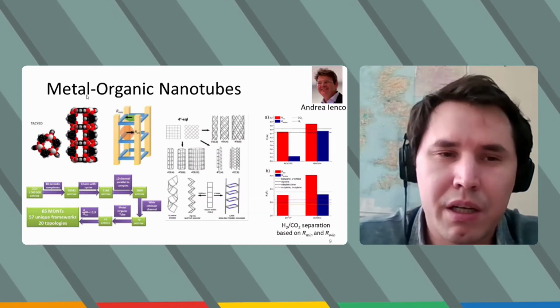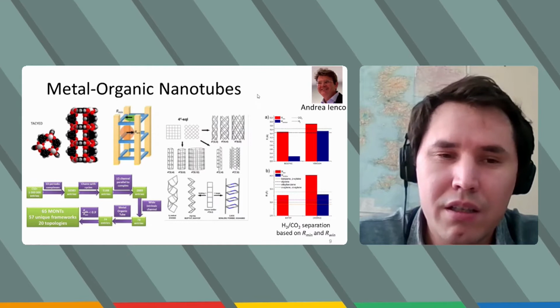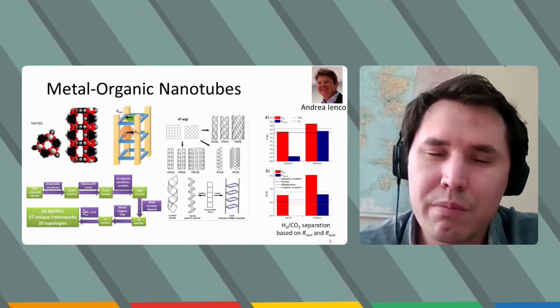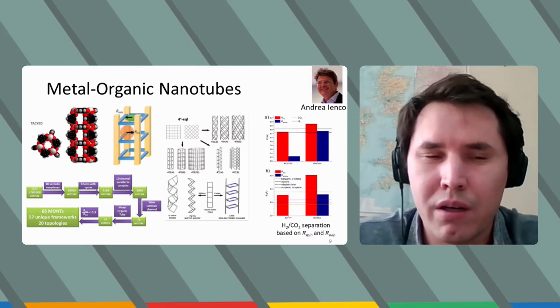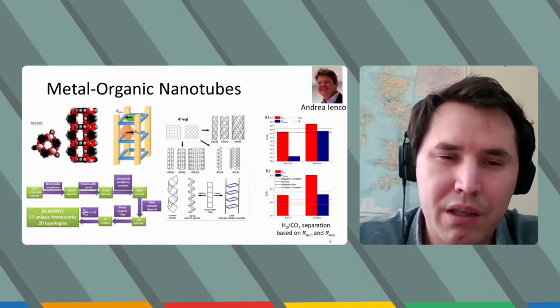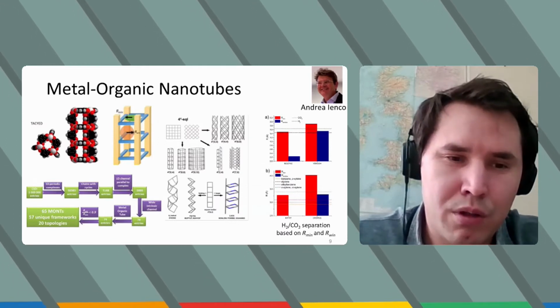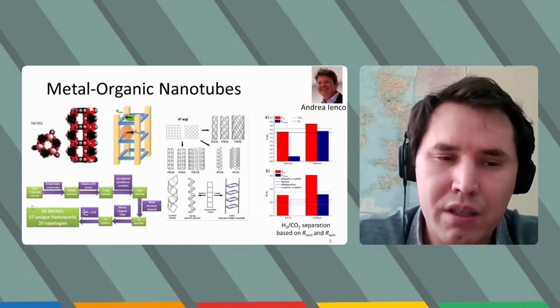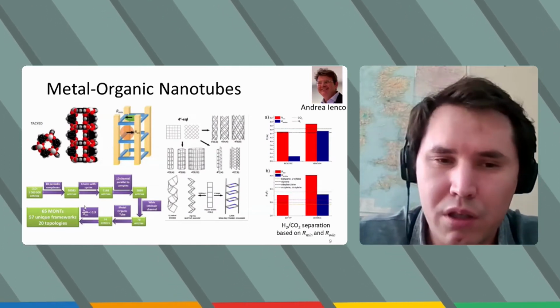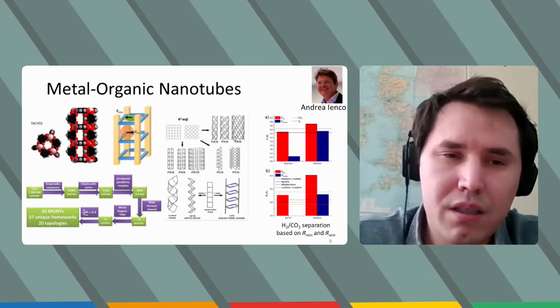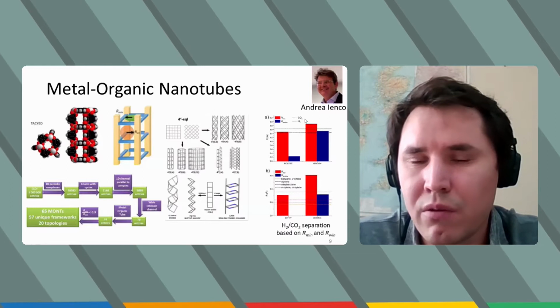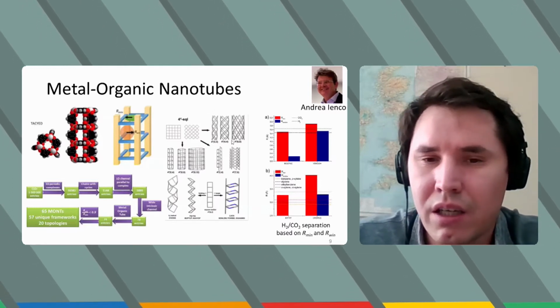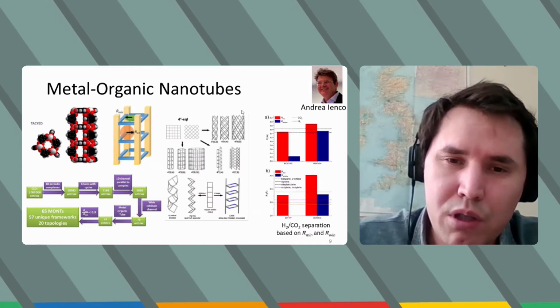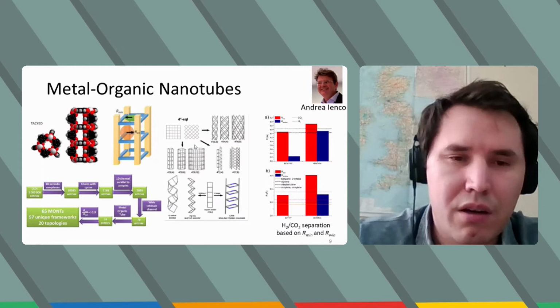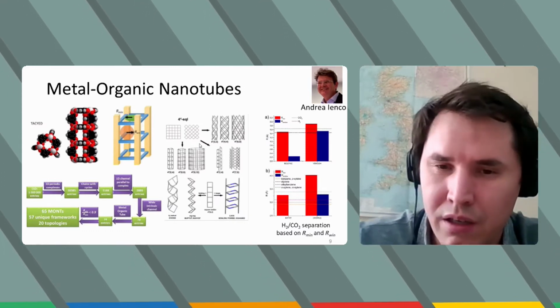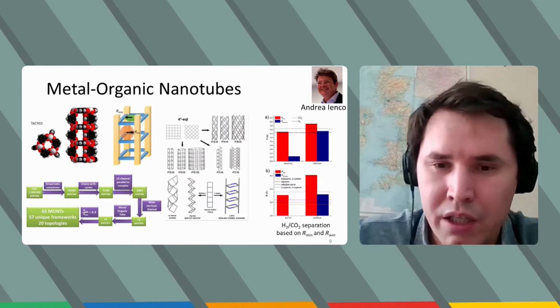A very hot topic is production of metal organic nanotubes. It is very curious. It is possible to make nanotubes not only from carbon, but also from metal organic compounds. And we found that there are only 65 metal organic nanotubes which are published in crystallographic databases. And these materials can be used for separation, for example, of carbon dioxide and hydrogen. And moreover, it is possible to assemble many other new topologies which have nanotube architecture.